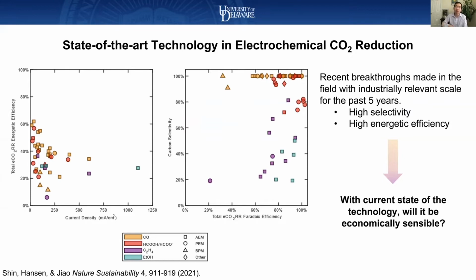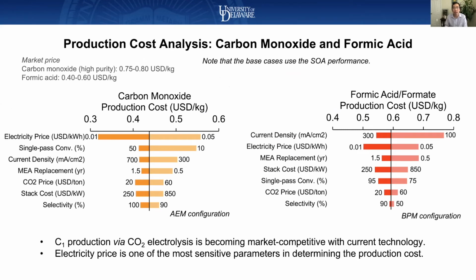We first did a survey on what the state-of-the-art technology reported in the field is for different products. We examined 4 major widely reported products: formate, CO (carbon monoxide), ethylene, and ethanol. And what we find is for C1 products, carbon monoxide and formic acid, they are very close. Our projected production costs are very close to the current market price if you can maintain the state-of-the-art performance. This is our conclusion. It's very close. Of course, there's still room for improvement.